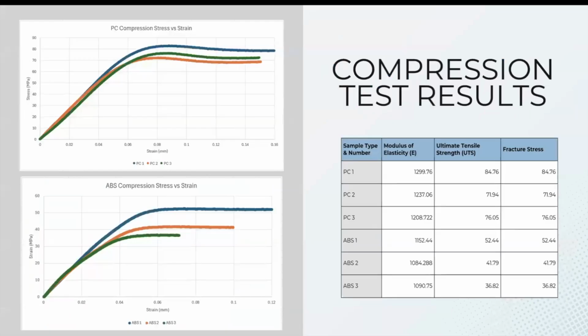So now moving into our compression test results, starting with the PC compression curves at the top, all three samples followed a pretty similar trend. They show a linear elastic region up to about 0.05 strain, followed by a peak stress between 72 and 85 MPa. After reaching that ultimate stress, the curves level off, which indicates yielding and plastic deformation.